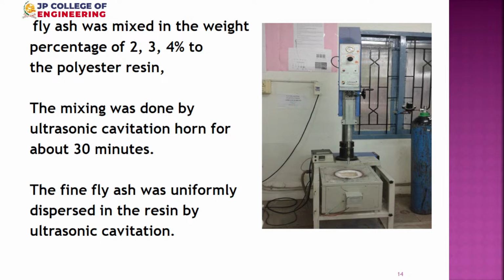In the place you put a crucible where you add the resin and then put the particle. The moment you put the particle, the fine particle will only float up, so you have to slightly stir them. Then you insert the top ram, which is ultrasonic and agitates at a high frequency. Then the fly ash will get uniformly distributed. This is the idea of ultrasonic cavitation, by which you can ensure fine particles are uniformly distributed in the resin. So this setup shows that.